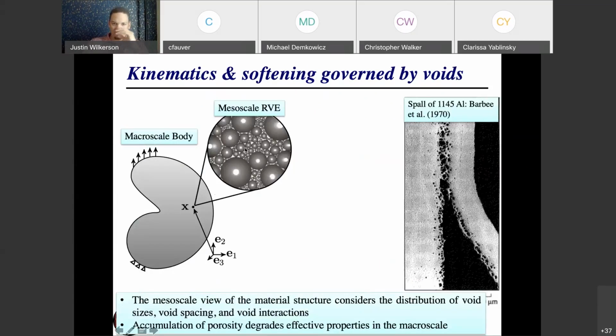And voids that I have in this mesoscale cartoon. And so I have distributions of voids that are nucleating and growing, and they're all working together to soften the material. In a brittle material, it'll be the same story, but with cracks. And so I will nucleate lots of cracks. The main thing that will be different in brittle materials is those cracks are highly oriented. And so there's quite a bit of anisotropy that's introduced, whereas for voids, especially in spall failure, the voids are fairly spherical. So the situation is a lot more isotropic.